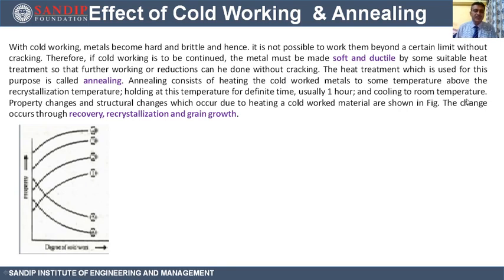Now, this cooling happens very slowly. We are heating the material in the furnace itself, and after the soaking time, that is after 45 minutes or 1 hour, we switch off the furnace. Heat addition is stopped at this juncture. Without opening the doors of the furnace, we allow the material to cool in the furnace itself. It takes a lot of time to cool the material to room temperature, and that is obviously the purpose of annealing: a very soft, ductile structure is to be obtained, but for that the cooling should be very slow.